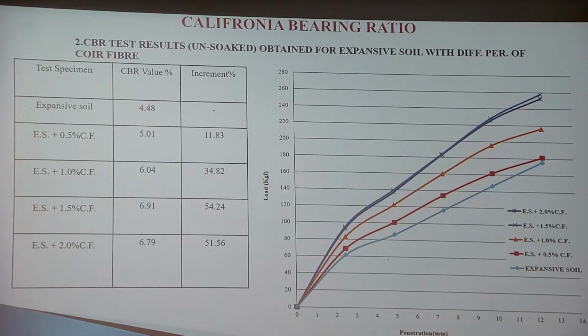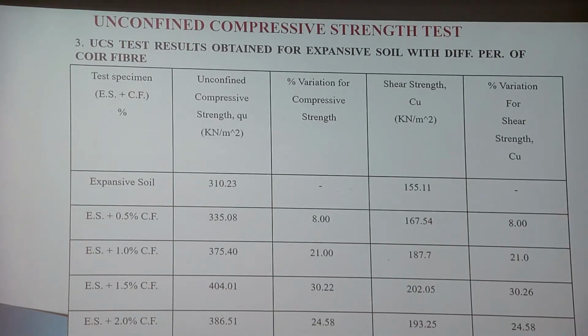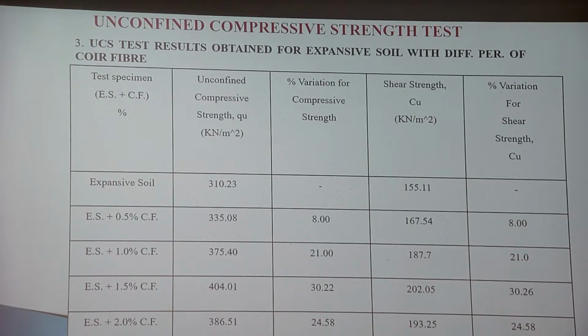UCS test result obtained from expansive soil with different percentages. At first we find the UCS value of the soil sample, which is 310.23. After that we mix different percentages of coir fiber. At first we mix 0.5% of coir fiber and find the variation, and finally the maximum value is at 1.5% of coir fiber. Again we increase, then the UCS value starts to decrease. Finally we conclude that this is the graph.